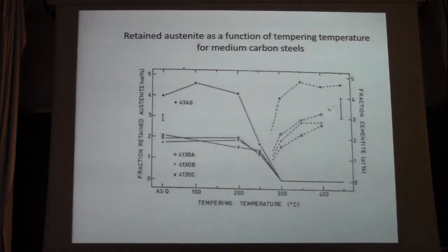Here is measurement, you know, these medium carbon steels, 4340, low alloy steels, this is a chrome moly steel, the 41XX steels. When they are quenched, they have retained austenite. Basically, the amount of retained austenite is a function of the carbon content, 2% for these chrome moly steels, which have a lower carbon content, and the 4340 has a higher carbon content. It may have retained austenite up around 4 or 5%. But then, when you temper within the tempered martensite embrittlement range, the retained austenite transforms to cementite. And now you've changed the microstructure and you've introduced particles on which fracture can occur.